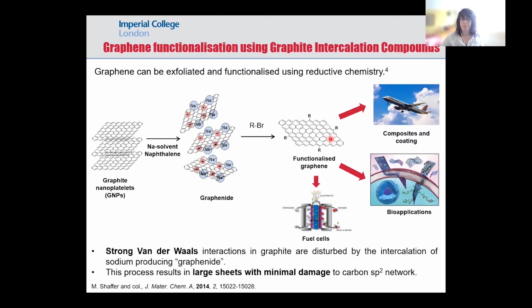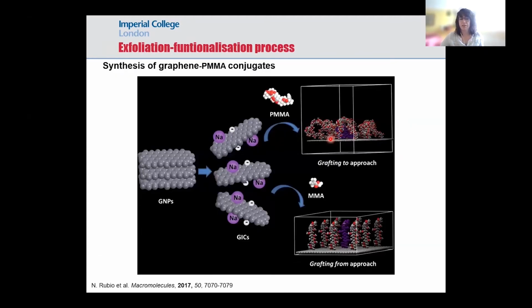in fuel cells. In one of the works that we have studied, we efficiently charged these graphites, and then we used different approaches to produce polymer-functionalized graphenes with polymethyl methacrylate, which is a good polymer to make graphenes more compatible with epoxy resins for application in composites. So we explored a grafting-to approach, where we previously synthesized the polymer and then grafted it on the graphene layer. Or we used the monomer. We added the monomer directly to the charged graphenes in a grafting-from approach, growing the polymer directly on the graphenes.